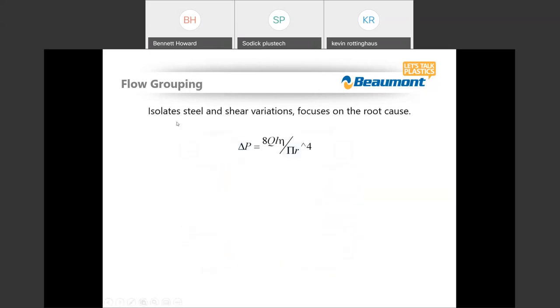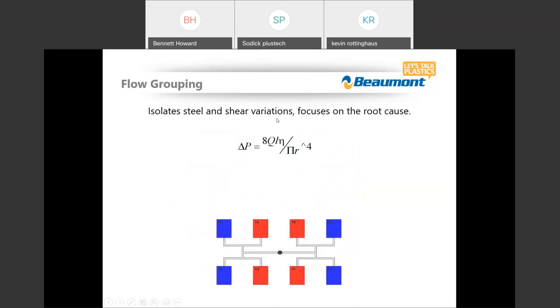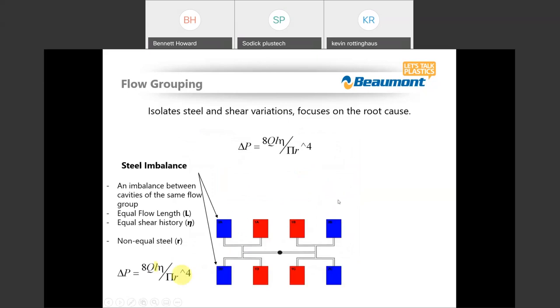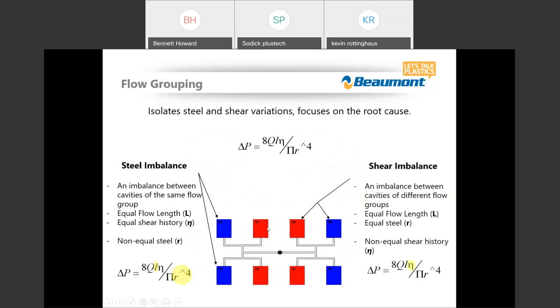So flow grouping is simply there to isolate your steel versus your shear variations. And that's going to allow you to concentrate on your root cause. I mentioned earlier, these four cavities are all filling with the same melt properties. Therefore, they should fill and weigh the same. If these four cavities in the center don't weigh the same within themselves, then it's a steel imbalance.